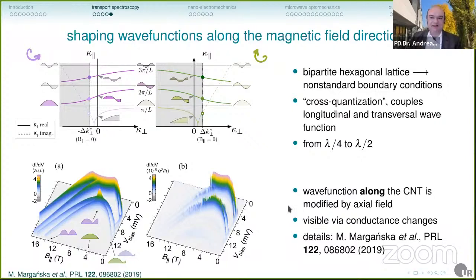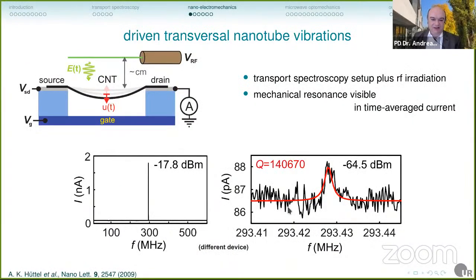Now let's switch gears a little bit and switch from the electronics, as I've already announced, to the mechanics. You've seen that this nanotube is hanging across a trench, so it can vibrate like a string resonator. And how can you show that? Well, in these low temperature experiments, there's actually a very easy way to do that. You hang an antenna on top, just contact free. It's basically just an open-ended coaxial cable. You apply a radio frequency signal, you sweep the frequency, and at some point you get in your DC current measurement a huge spike.